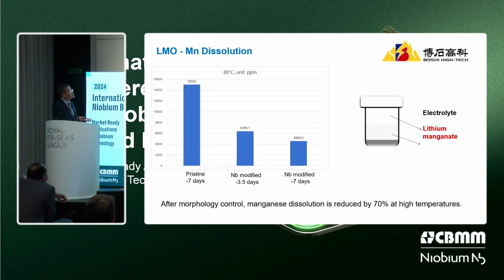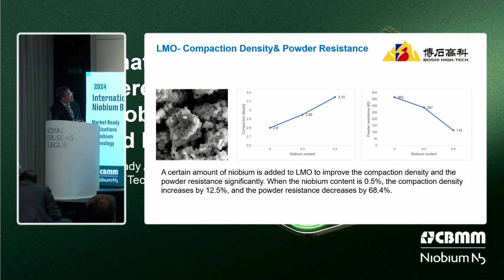Yeah. Okay, let's show some data. Here is manganese dissolution without niobium and with niobium modified. In 7 days, we can find the manganese dissolution decreased 70% even at high temperature. For LMO, high temperature cycling stability is also a very weak point for this kind of material. And here, with niobium increased, the compacted density also increased. And this one is the powder resistance decreased. Here increased more than 10%, and the powder resistance decreased more than 60%.